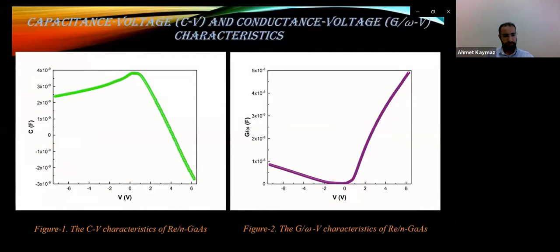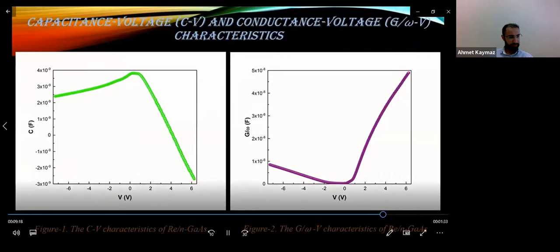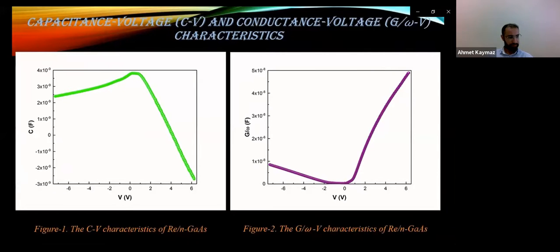As can be seen in figure 1, the CV plot has an anomalous peak behavior at about 0.5 volts in the forward bias region, and an intersection occurs at about 4.2 volts, and then capacitance values become negative after this intersection. This abnormal peak was attributed to surface states by some researchers. However, recent studies have shown that this may be due not only to surface states, but also to the series resistance of the devices.